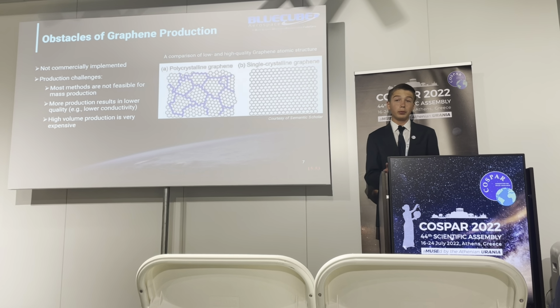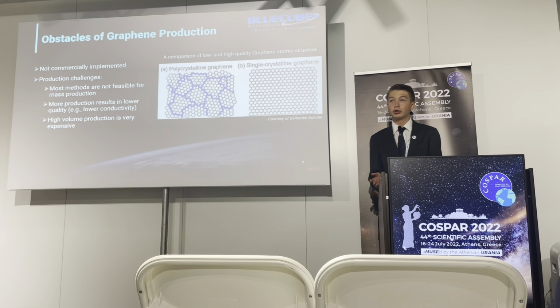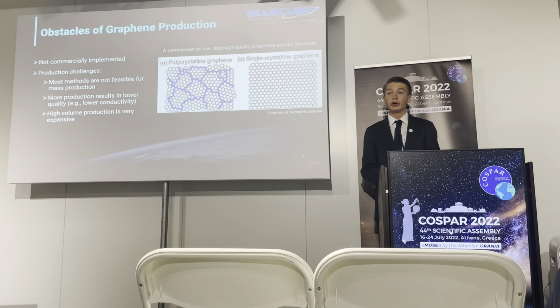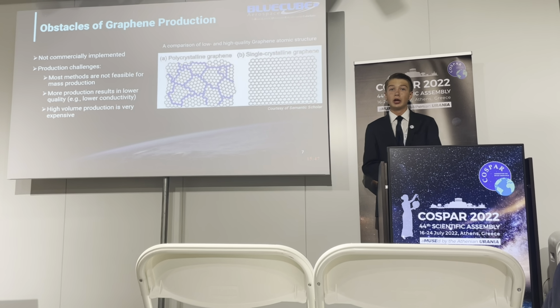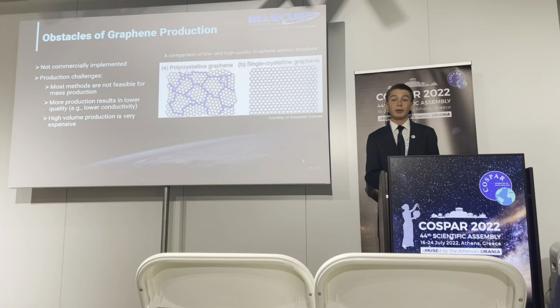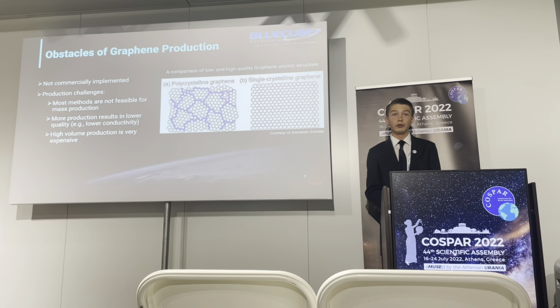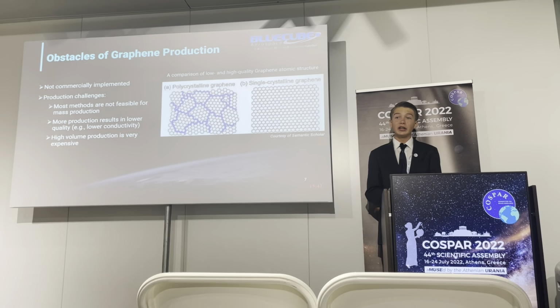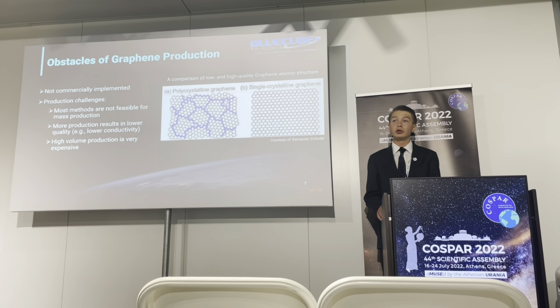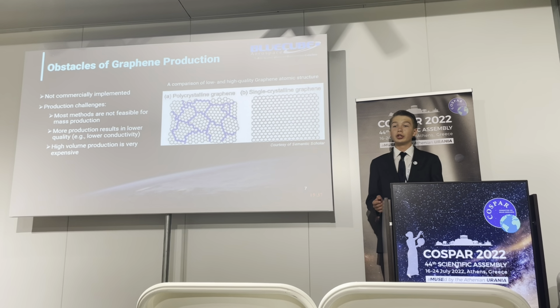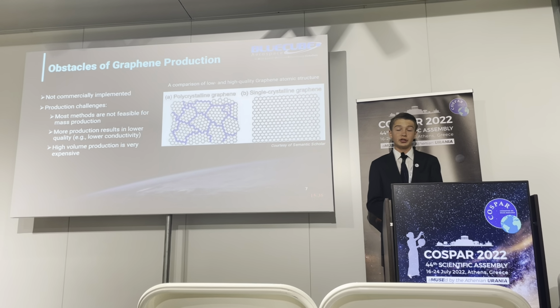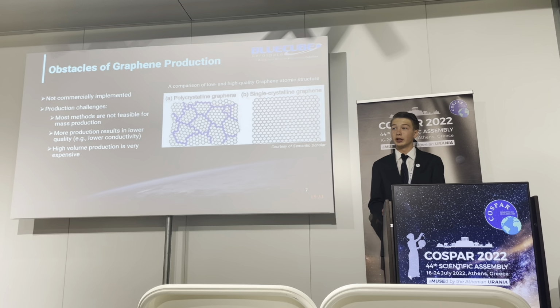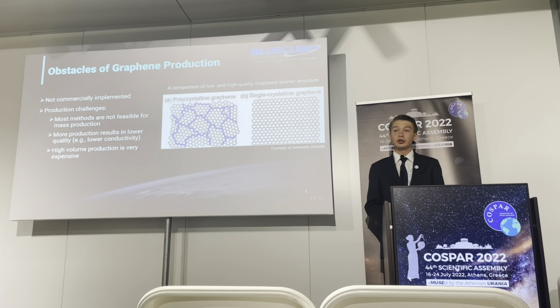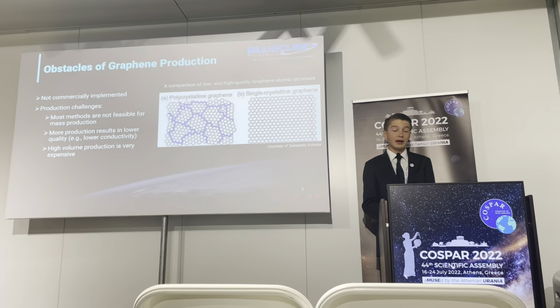So the main reason why graphene hasn't been commercially implemented, as I mentioned earlier, is due to all of the production challenges. Typically, the majority of production methods only produce a very small amount of graphene, and the ones that are easily scalable generally produce lower quality graphene, which can limit some of its qualities, such as conductivity and other things, making it harder to use in applications and decreasing some of its benefits.